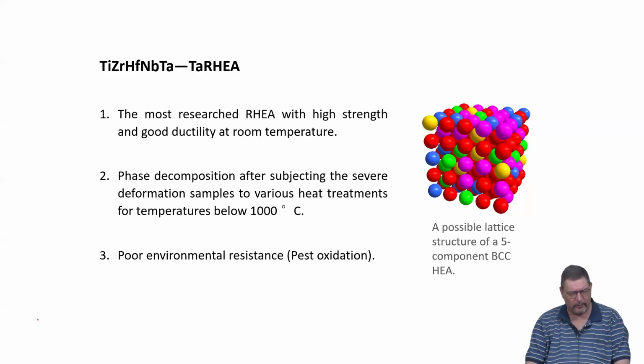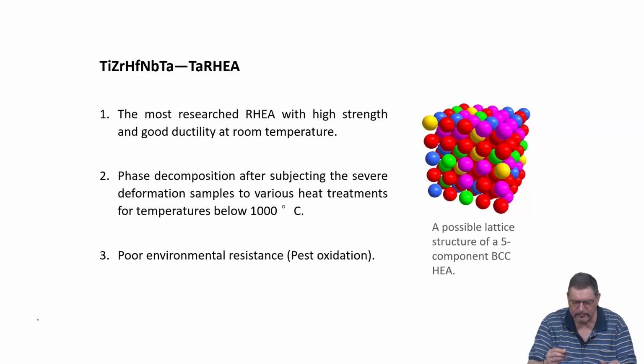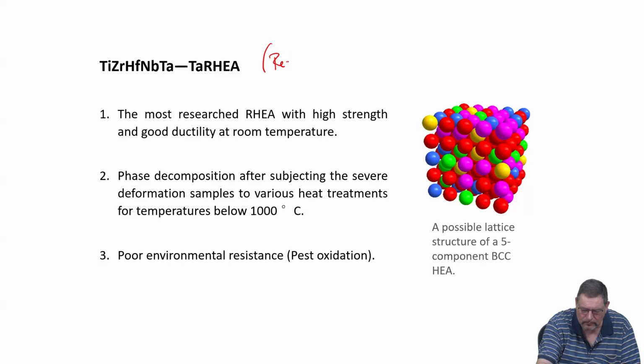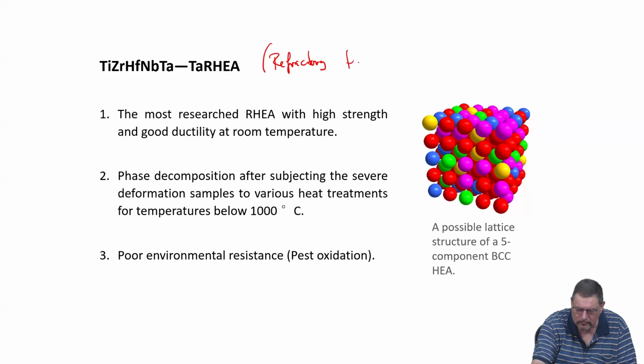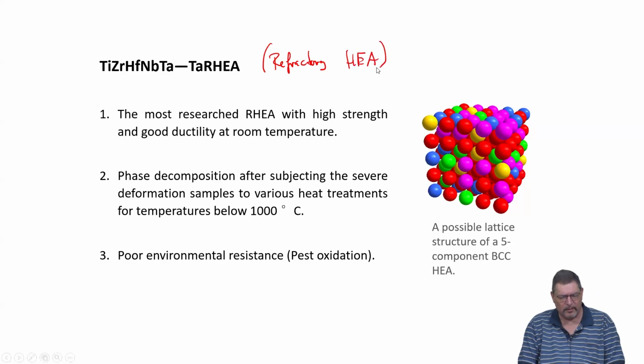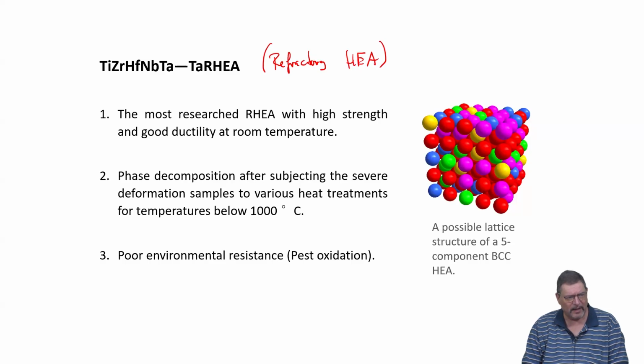When we now think of these RHEAs, the refractory high entropy alloys, then this alloy, the titanium, zirconium, hafnium, niobium, tantalum, is really the most researched one so far. It has very high strength up to very high temperature, and at the same time good ductility at room temperature. So it can be machined, it can be processed at room temperature, which is very important for any application, but it has a very high strength up to high temperature. So it's really something like a very model-like material for high temperature applications.